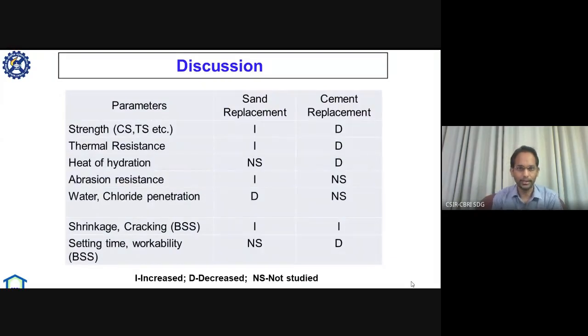So overall, if we replace the sand with stone slurry, any kind of stone slurry, whether it is marble or limestone or granite or sandstone, it will increase the strength attributes, whether compressive or tensile. It will increase the thermal resistance, abrasion resistance, shrinkage, cracking, etc. But if we replace the cement in a higher amount, more than say 20%, it will at the same time decrease the strength and thermal resistance, and heat of hydration will of course be decreased, and the setting time will be reduced because it forms nucleation sites in the cement composite mix during hydration. And workability, of course, will also be decreased due to its higher fineness.